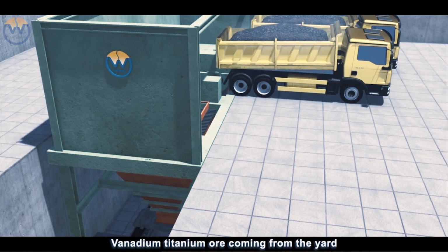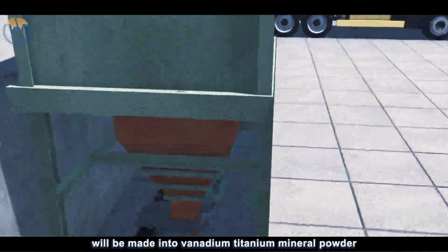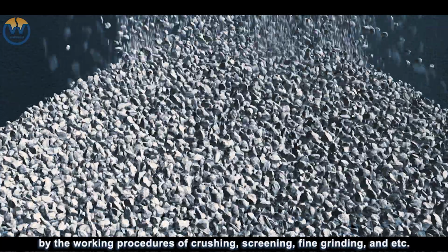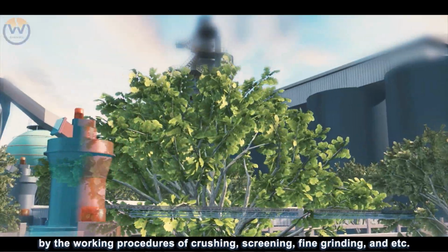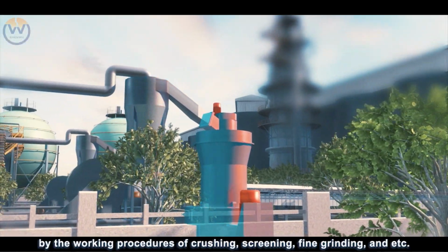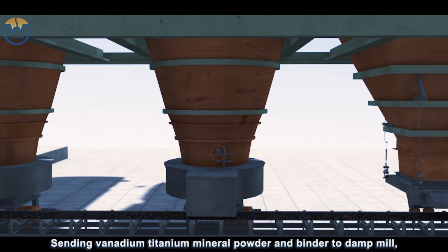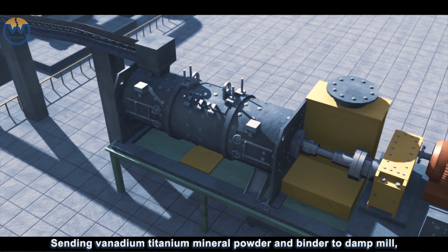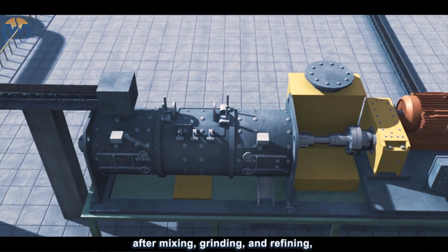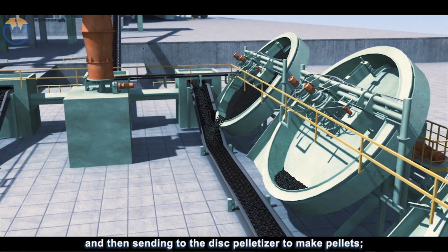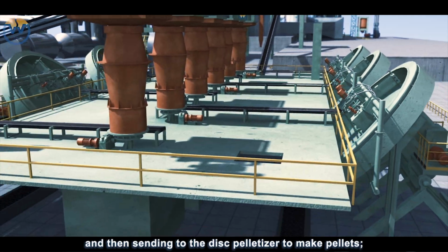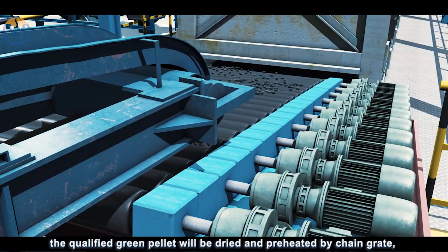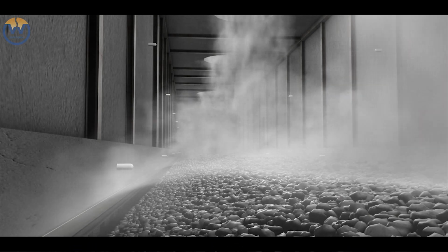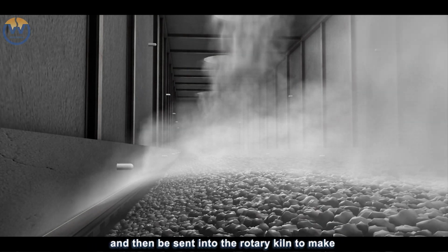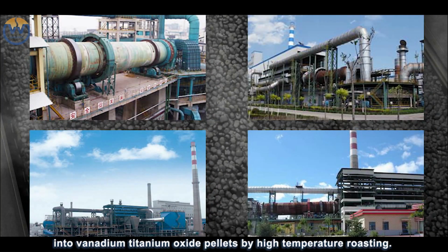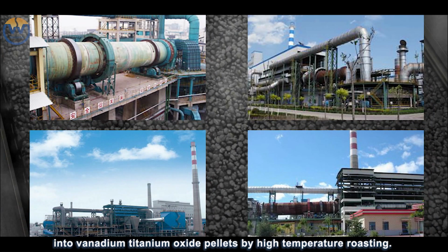Vanadium titanium ore coming from the yard will be made into vanadium titanium mineral powder by the working procedures of crushing, screening, fine grinding, and so on. Vanadium titanium mineral powder and binder are sent to a damp mill after mixing, grinding, and refining, and then sent to the disc pelletizer to make pellets. The qualified green pellets will be dried and preheated by chain grate, and then sent into the rotary kiln to make vanadium titanium oxide pellets by high temperature roasting.